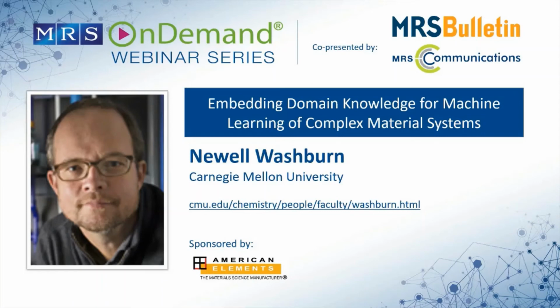What we're doing currently, and we have some papers that are just about to head out the door on this, is estimating the prior distributions in a Bayesian context. You could get at that from just repeating the same experiment over and over again, just to see what the intrinsic variance of the system is, and then you can mathematically model that with a Laplacian prior. So you can do similar regression-type approaches where you're using these Laplacian priors as a way of embedding the underlying distribution. Because you're carrying a full distribution from the middle up to the top, you get this propagation of uncertainty, which, as long as it doesn't blow up on you, can give you meaningful estimates for the uncertainty in the overall materials or system properties.